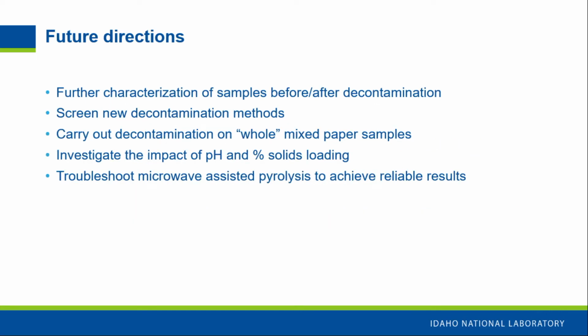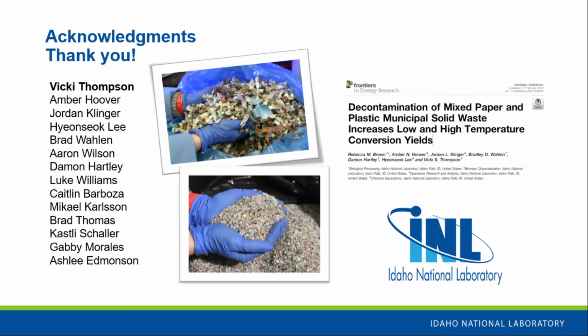Our future directions are to further characterize these samples before and after decontamination, screen new methods, and carry out decontamination on whole paper, so rather than just doing different fractions of the paper, we want to use the combined whole sample. We also want to investigate the impact of pH and percent solids loading. We tend to do our enzymatic hydrolysis at a low solids loading, but the industry really wants a high solids loading. So how does the solids loading impact pH and our yields? Our next step for pyrolysis is to troubleshoot our microwave pyrolysis and get better, more reliable results.